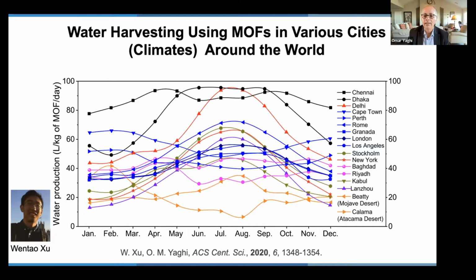day. The nice thing is that the MOF stays in the device for many, many years, for 5 to 6 years. At the end of this journey, if the MOF is not performing well, you can take it and separate the components by using strong acid and recombine them in water to make the same material. So it's completely recyclable with zero waste. And this pertains to the subject of this conference, which is the sustainability.